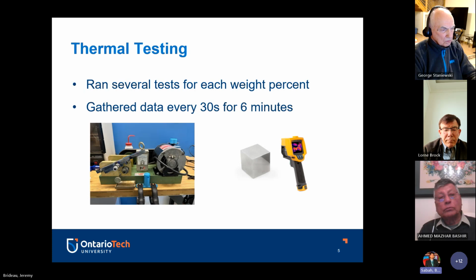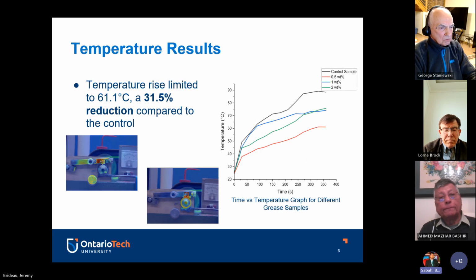What we actually found was when we added 0.5% graphene inside the grease, we had a peak temperature of 61.1 degrees Celsius, which is a 31.5% reduction in temperature when compared to the samples without any graphene in it.